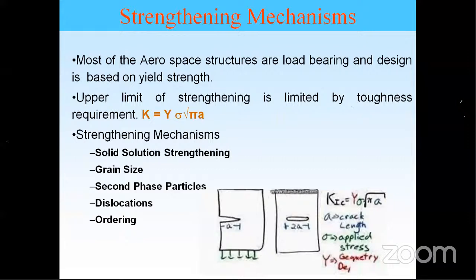The upper limit of the strengthening is limited by toughness. I can give an example: I have used both maraging steel as well as a material called bearing steel, the 440C, that contains about 1% carbon. Both have nearly 1800 to 2000 MPa strength. The problem with 440C is that it is highly brittle, and maraging steel is ductile. Maraging steel offers a fracture toughness of nearly 90 MPa√m, whereas 440C gives fracture toughness of nearly 10 MPa√m. That means it is brittle.